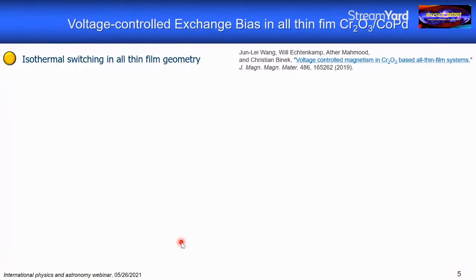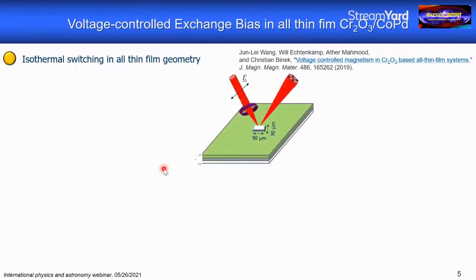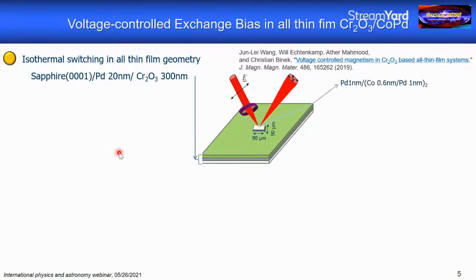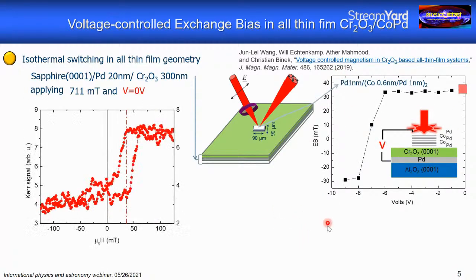So we had a bit of a race, and I show you just our first results on switching in all thin film. The publication of that result took us a very long time, but here you see it. So basically, first of all, we deposited a film of magnetoelectric chromium oxide, or chromia, on top of this palladium electrode, and we did this by pulsed laser deposition because the film is so thick.